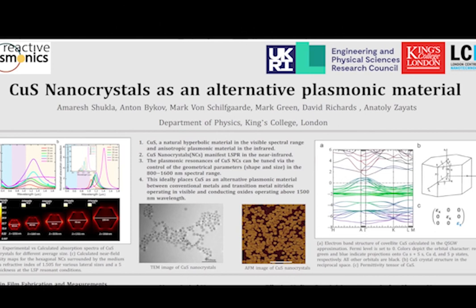Subsequently, these nanocrystals show a dominant localized surface plasmon resonance in the near infrared, which has been demonstrated to be widely tunable by changing the size and shape of the nanoparticles, and its range can be between 800 to 1600 nanometers.